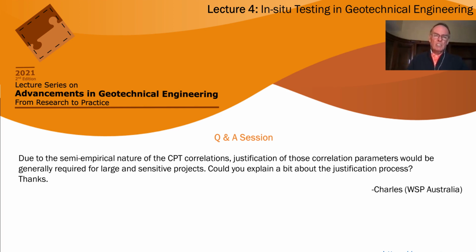The sleeve friction is telling you what the remolded strength is, but the peak strength may be off because of the effect of bonding. And so if you read that 2016 paper in the Canadian Journal, hopefully it walks you through why it's important to identify microstructure. And that's why I spent a little bit of time during this presentation, so that you know whether or not the semi-empirical correlations can be used with confidence.